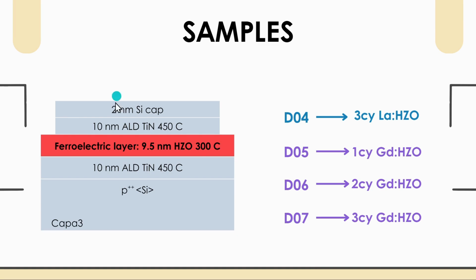Each sample has a 2 nanometer silicon capping layer on top to protect the stack, and 2 layers of 10 nanometers titanium nitride electrodes on the top and the bottom, and 9.5 nanometers hafnium zirconium film in the middle, which is the ferroelectric material, and a P++ silicon substrate at the bottom. What makes them different is the dopant type and concentration in the ferroelectric layer.